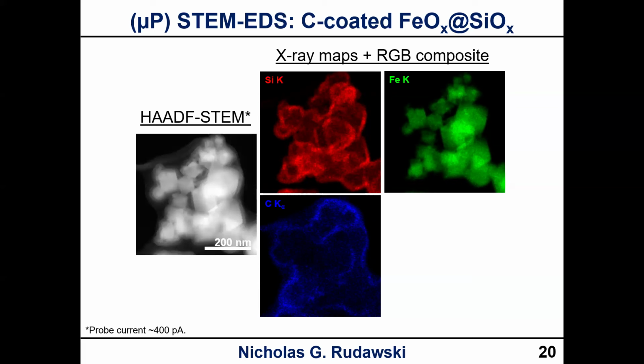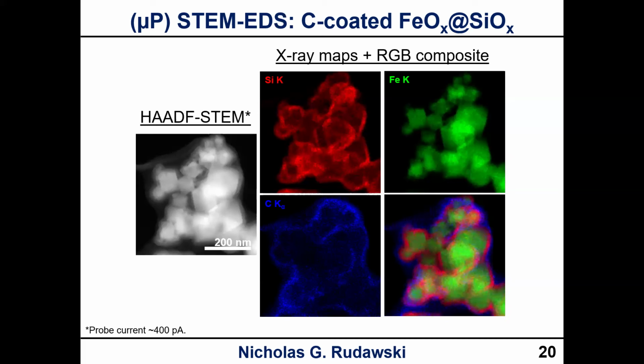You can see very clearly that we're resolving the iron in the core, but we're also resolving the silicon in the shell and the shell on top of the silica shell, which is organic, okay, the carbon. So these maps, you notice with the silicon K and iron K, I didn't specify alpha. That's because both the alpha and beta peaks contribute to those maps. With the carbon, there is only an alpha peak. So that's why I specified alpha. If we overlay it, we can see very clearly, nice rendering of this, and that we have the structure that we were expecting to have here.